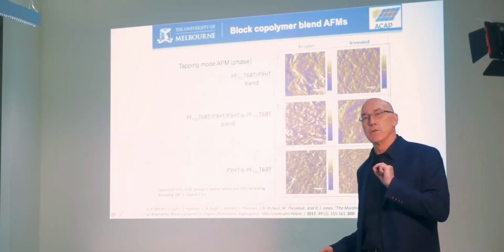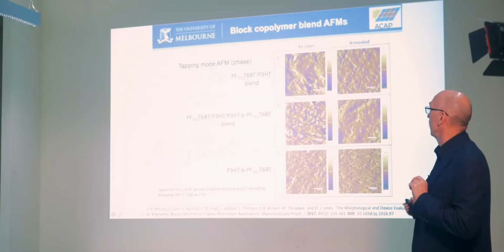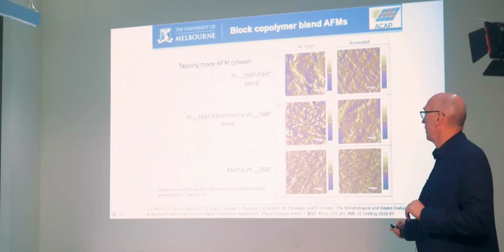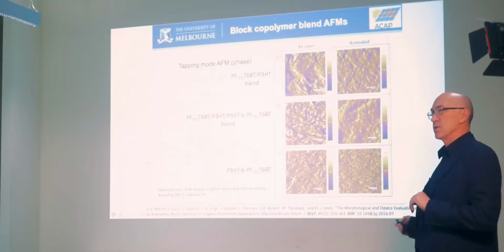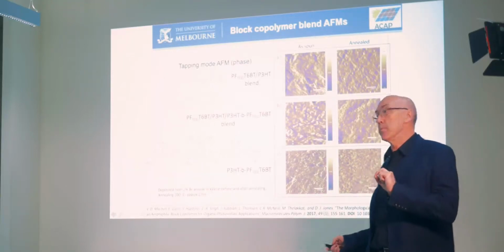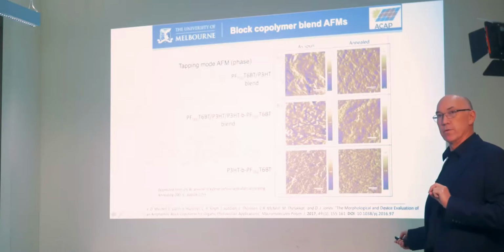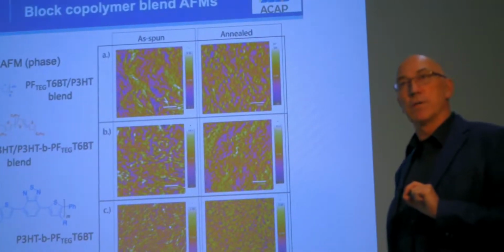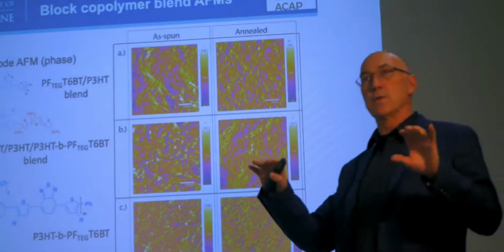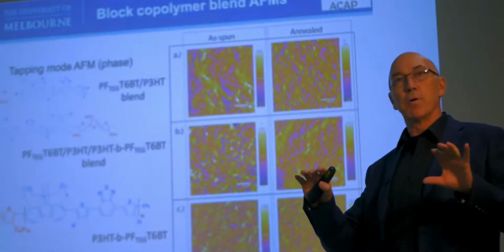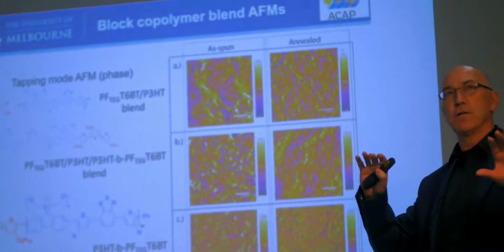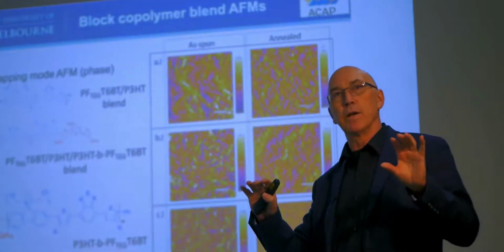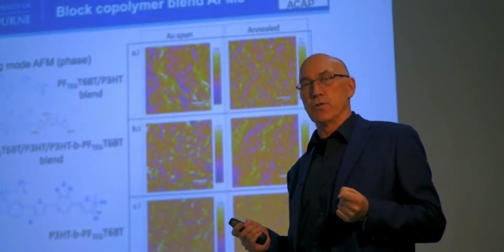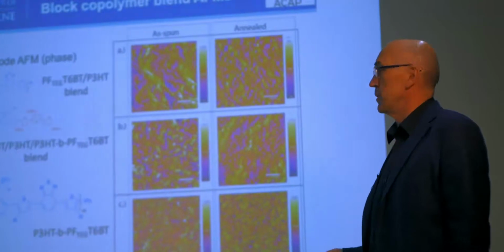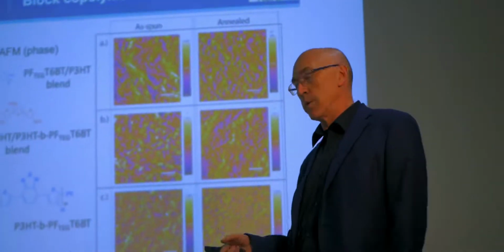Then when we made a thin film, we were able to show that if you've got a blend, it doesn't work. If you have a blend of the di-block and the homopolymers, it also doesn't work. But when you have the pure di-block, you get really good control of the morphology. And so this was basically a proof of principle to say that you can use a di-block copolymer where you've changed the free energy, make one hydrophobic, one hydrophilic, to control that phase separation. But these were not really good materials. This was just basically going on what we had before.